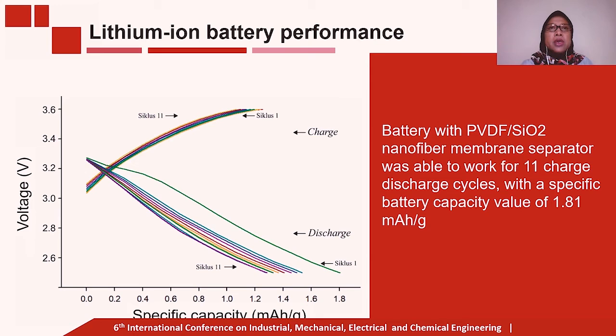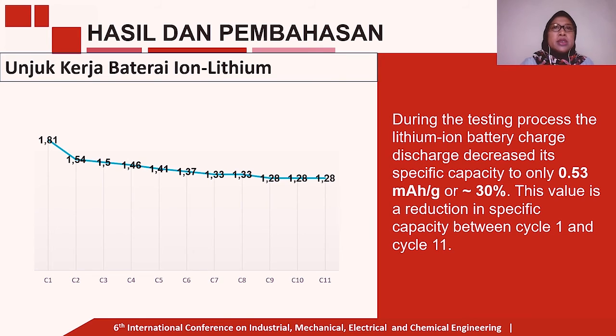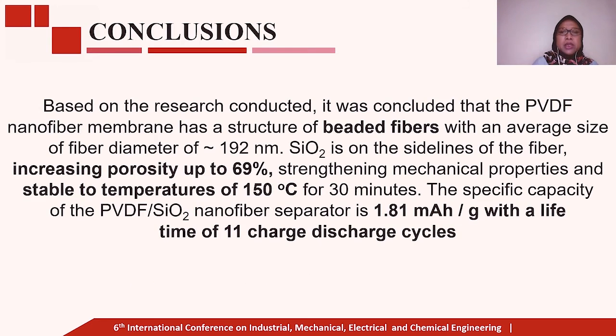This is the electrochemical test result. Lithium-ion battery performance. Battery with PVDF SiO2 nanofiber membrane separator was able to work for 11 charge-discharge cycles with a specific battery capacity value of around 1.81 mAh per gram. During the testing process, the lithium-ion battery charge-discharge decreased its specific capacity to only 0.53 mAh per gram or around 30%. This value is a reduction in specific capacity between cycle 1 and cycle 11.